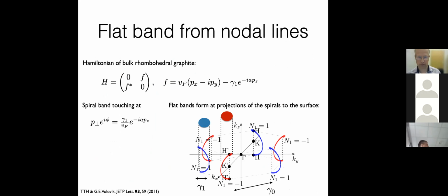You can argue the presence of this flat band from bulk rhombohedral graphite. If you now write the Hamiltonian of full bulk rhombohedral graphite in this approximation, you find that it contains a spiral nodal line. So there is a line of band crossings which form these spirals, and at every valley there is a single spiral. The spiral has a topological charge, which is basically the spiral helicity. When you project the spiral to the surface, you have a region of zero energy. And this is basically the flat band.